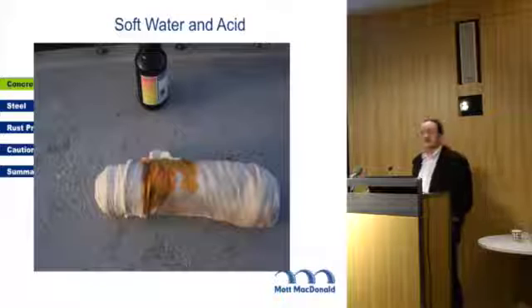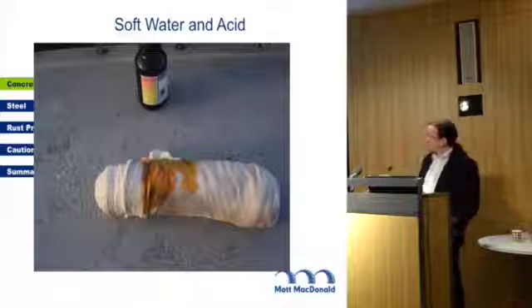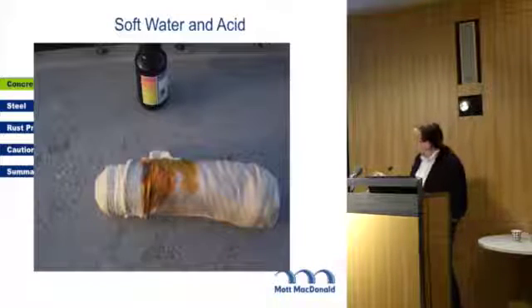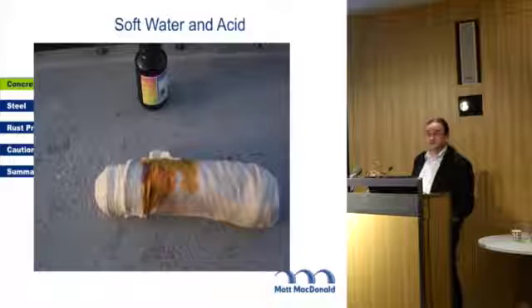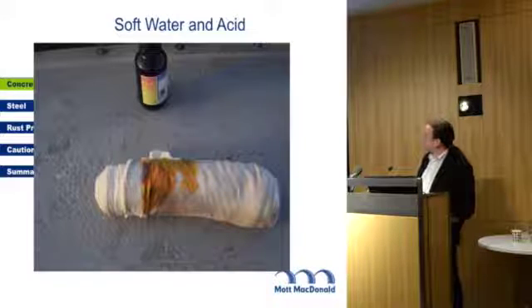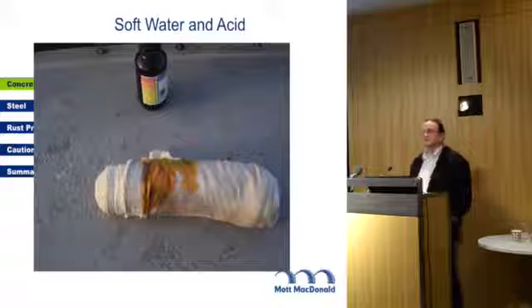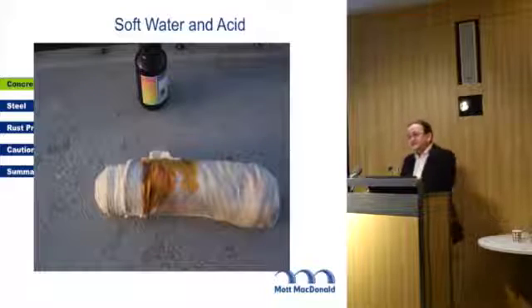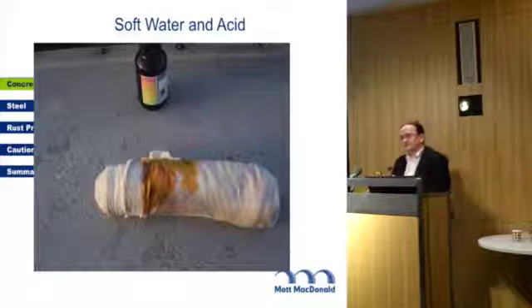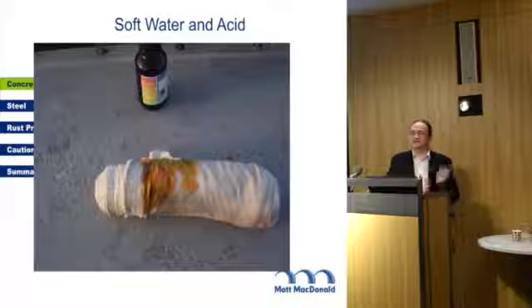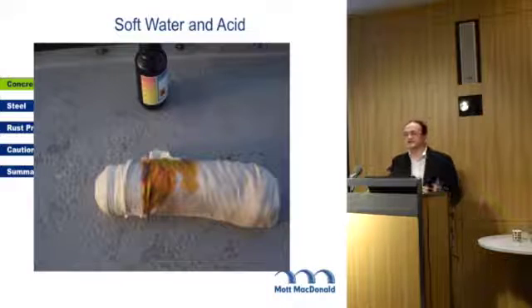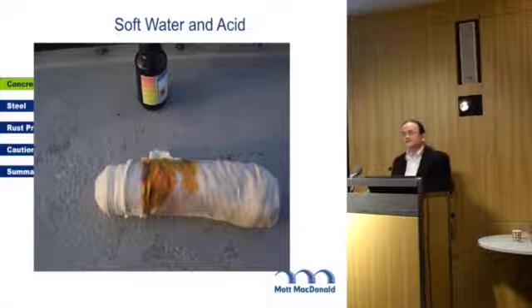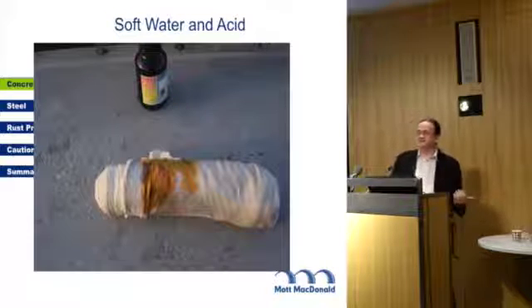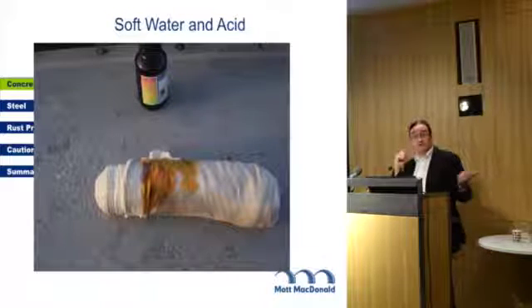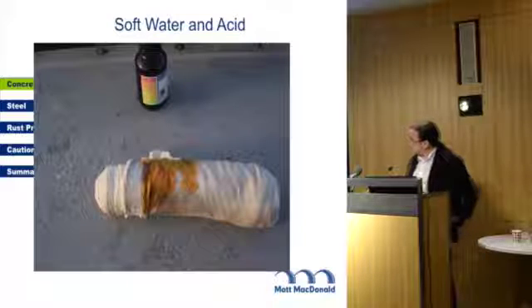That is a rag that I dangled into a tank of sewage and scraped up the side of the wall. That's universal indicator, measures pH between 1 and 14. That little red bit there says the wall of that tank was at pH 1. If you lived next to a sewage treatment works and it smelled, historically you just accepted that was because you lived next to a sewage treatment works. In more recent times, you complained to the owners of the sewage treatment works, who are very into customer care these days, and they come along and they put a lid on it.